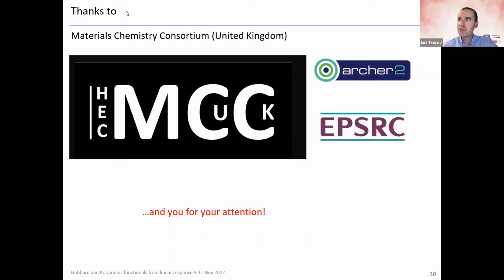Just maybe a little addition: DFT+U plus V is more accurate. So I would rather trust DFT+U plus V rather than DFT+U. Maybe it's not always better, but I would rely more on DFT+U plus V. And then just a reminder that neither DFT+U nor DFT+U plus V are the methods for band gaps. Tomorrow you will learn about Koopmans functionals. So those are the functionals for accurate band gaps, while Hubbard functionals only improve band gaps. Yes, so that's the message.